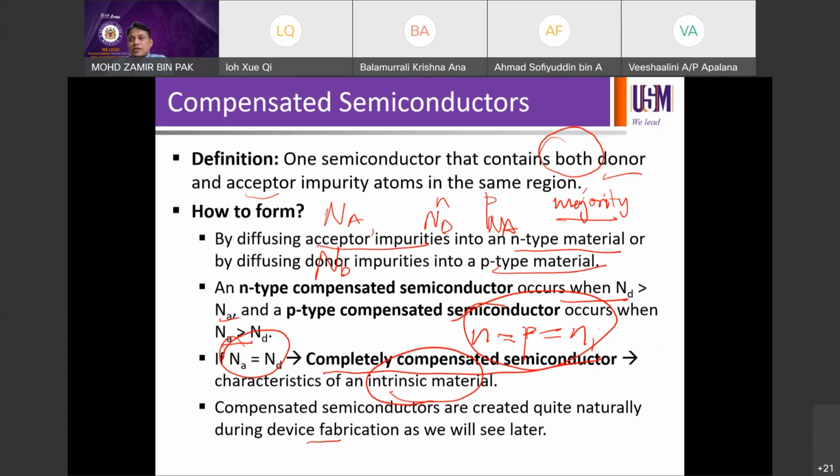So what you can do is, instead of starting off with intrinsic undoped silicon, you can actually reverse the polarity by doing compensation on purpose. You can just incorporate more dopants into the n-type wafer until it becomes compensated. Then you effectively have your intrinsic wafer to work with. So this can be done as a trick as well. Because if you don't have the wafer, you can just compensate the semiconductor to get intrinsic instead of starting off with intrinsic. But of course, you have to control the process well to make sure that it becomes intrinsic as intended. Okay, so let's just stop here.